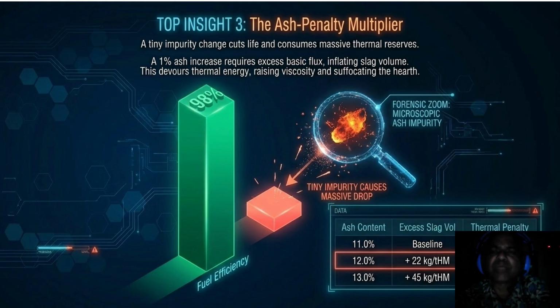The bar on the left represents your fuel efficiency. See that teeny coral block? That's a microscopic ash impurity. It looks insignificant, but look at the table. A move from 11% to 13% ash content, just a 2% swing, requires an additional 45 kilograms of slag per ton of hot metal to flux out.